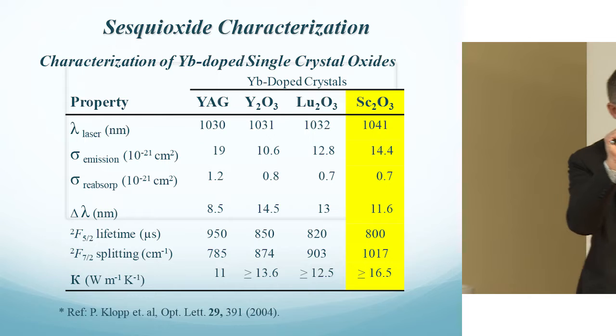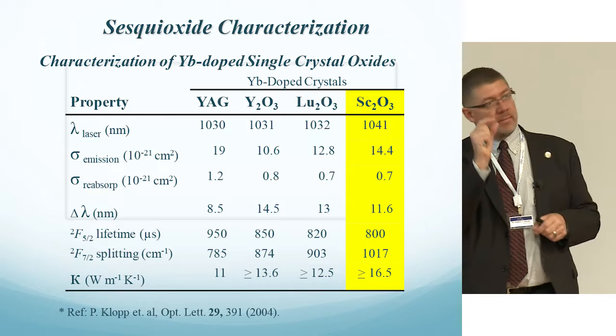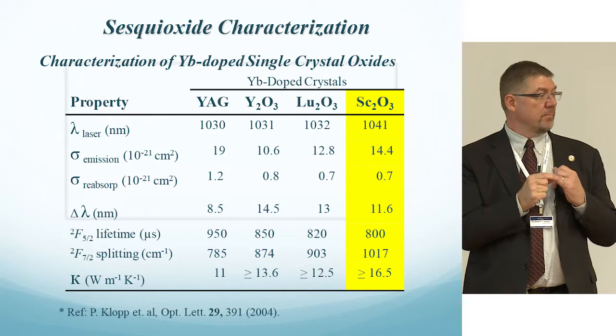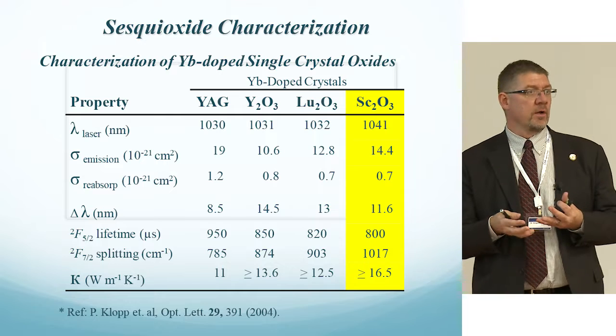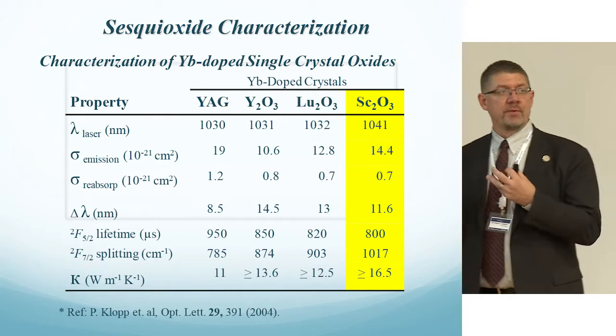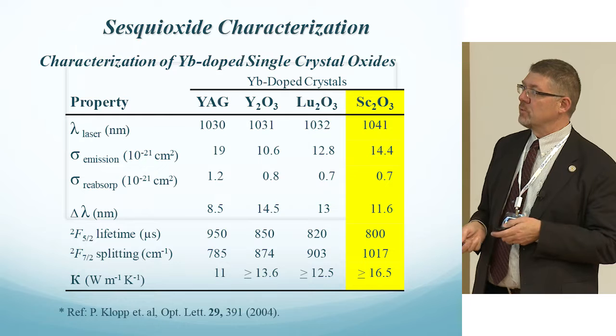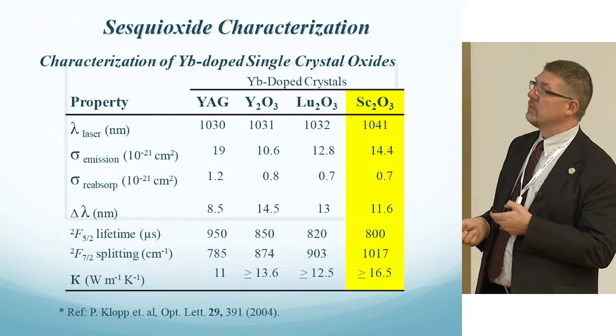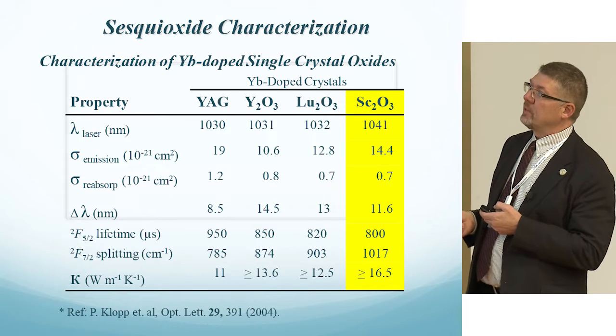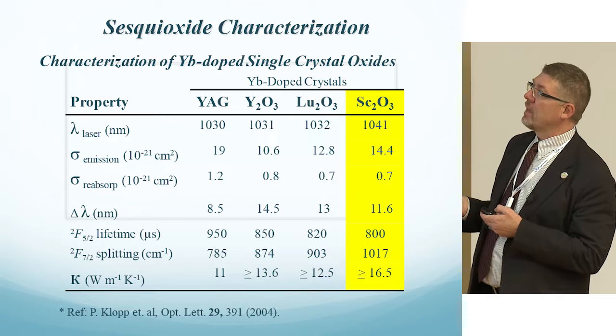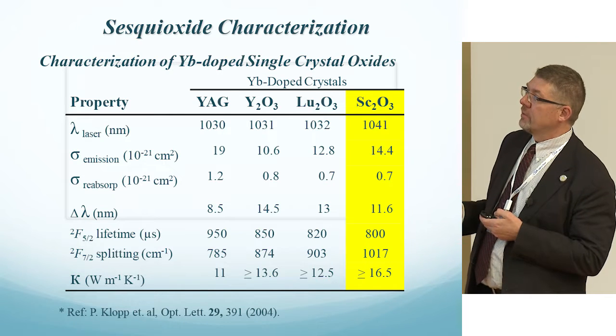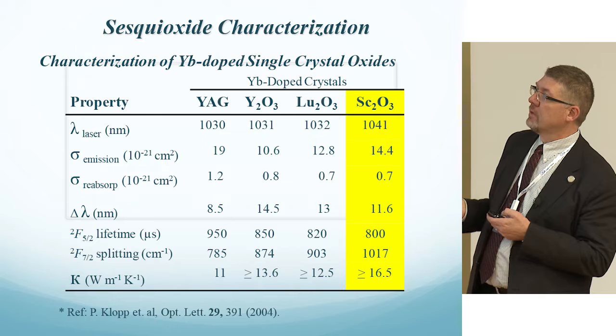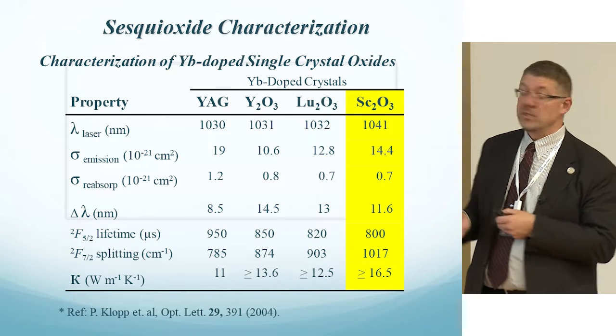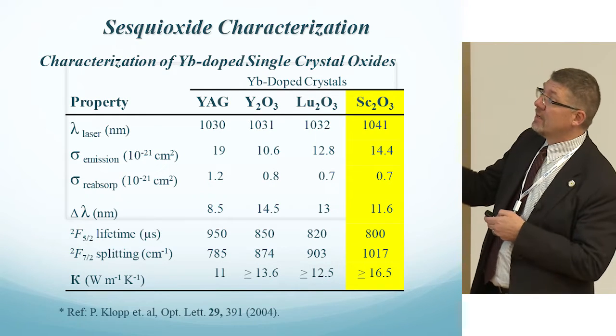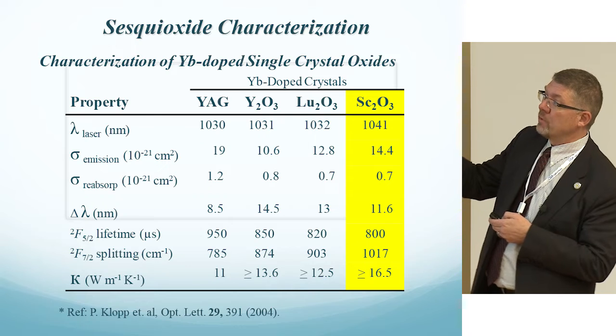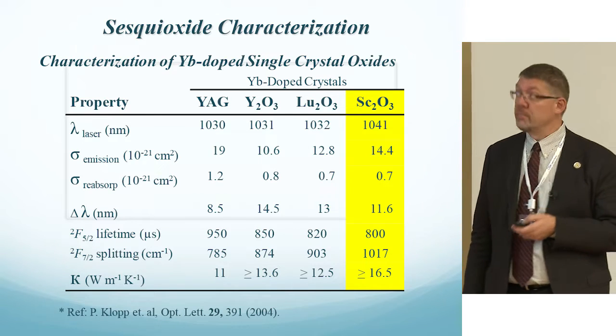temperature. So the groups in Hamburg, Germany have been able to grow pieces that are about the size of a thimble, and then it goes off course. So large pieces for industrial situations aren't very readily available. And why put the ytterbium in? So for something like scandia with the high thermal conductivity, here's the scandia ionic radius, and here's ytterbium, and it matches up pretty well. It's not as bad as going up here to neodymium, where you've got a much higher ionic mismatch.